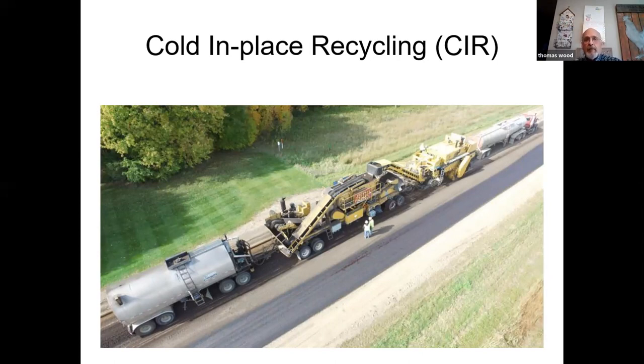Okay, first we'll talk about cold in place recycling. This is a picture I've got of a train. Up here is a water tanker. Here's a 12 and a half foot mill. It feeds into a screening, crushing, mixing plant, which drops the material in a windrow. I believe this is a foamed asphalt job, so this is a hot flat tank with 280, 300 degree asphalt binder in it. And then back behind here is a paver.